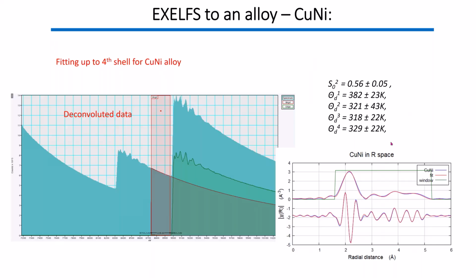Yeah, you can choose whatever shell you want to do. I don't think that's a problem in the software. You can always do that from a simulation point of view. If one wanted to do EELS or EXAFS in the TEM, extended energy loss fine structure, I do suggest doing simulation in the first place before heading for any practical things, because otherwise you can be very much lost if you're not so familiar with the machine and the technique you are using.